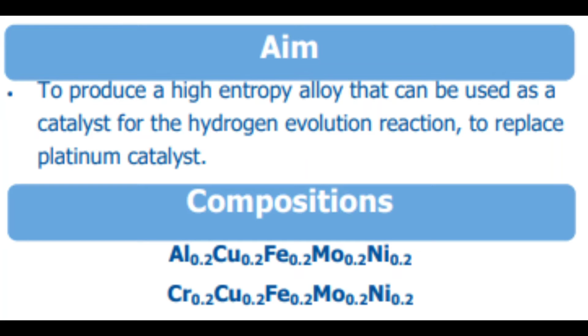The composition of the high entropy alloys was selected based off thermodynamic equations to determine which combinations would be able to form high entropy alloys, as well as selecting elements that performed well as catalysts for the hydrogen evolution reaction. The compositions selected were aluminium, copper, iron, molybdenum, and nickel, and chromium, copper, iron, molybdenum, and nickel. The main difference between these two combinations is that one contains aluminium, the other contains chromium. The other four elements are kept the same between each of these compositions. An equimolar composition was selected for both.